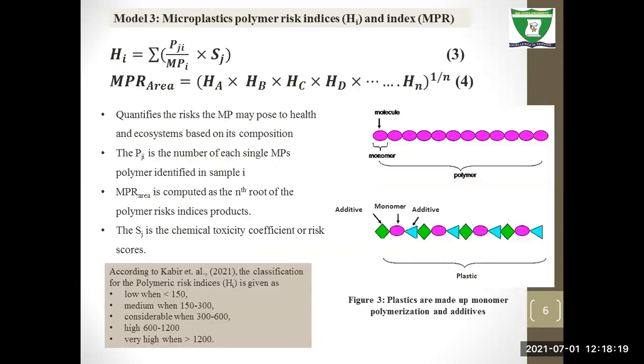Then we can have the microplastic polymer risk indices and index. Indices is for the sample, while the index is for the entire area. The polymer risk indices evaluates the contamination of microplastics based on the polymer type. So if you have a sample that you analyze and you have maybe PP, PET, different types of polymer identified in the sample, this model is used to estimate the polymer risk based on the different polymers identified.